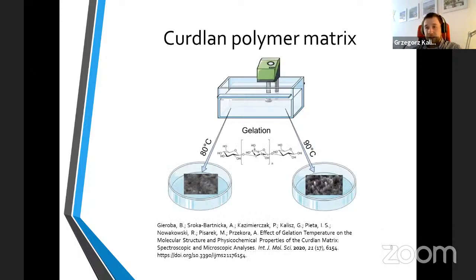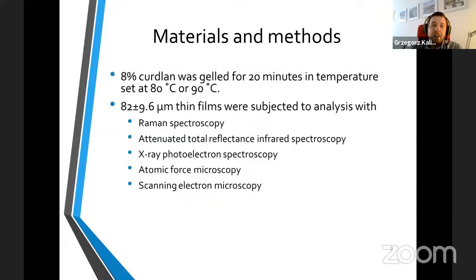And our first experiment was on the Curdlan polymer matrix. It was published one year ago. We prepared it in a water bath at two different temperatures, which we chose as 80 and 90 degrees. This was also prepared by Dr. Agata Przekora-Kuśmierz. After gelation for 20 minutes, films were cooled down, dried, and the acquired films were subjected to Raman, IR, XPS, and to microscopic techniques, AFM, which is atomic force microscopy, and scanning electron microscopy.